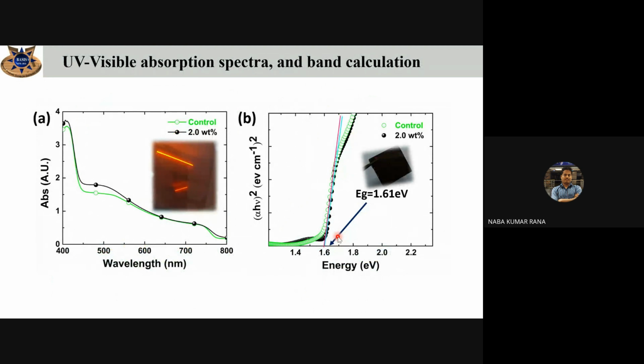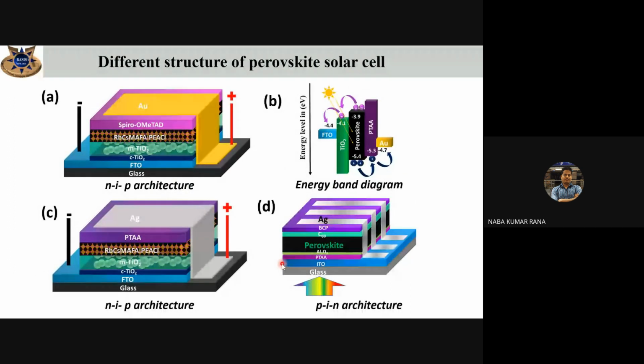The topic is the role of Al2O3 nanoparticles during the fabrication of high efficiency perovskite solar cells. In the inverted architecture we use a PTAA layer, that is the hole transporting layer, on top of the ITO layer, and we insert Al2O3 nanoparticles between the perovskite and the hole transporting layer. The advantage is that the Al2O3 nanoparticles improve the wettability between the perovskite layer and the hole transporting layer. We tried different concentrations, but at smaller concentrations we found that charge carrier extraction from the perovskite layer to the top and bottom electrodes increases, which helps to increase the efficiency of the device.